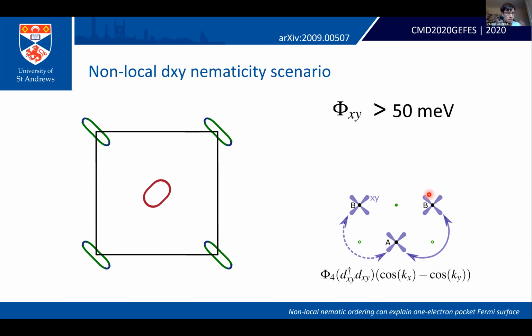So this is the main idea that we've had, that we think can explain many of the experimental properties. If you assume that nematicity is also strongly present within the dxy orbitals, specifically larger than the nematic term in the dxz and dyz orbitals, then you can reproduce the electronic structure that is observed with ARPES.